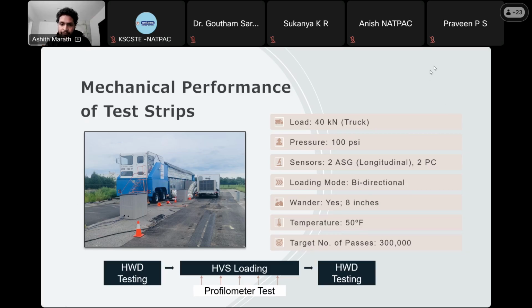And the testing plan was to conduct HWD testing. Again, the HWD is the heavyweight deflectometer, which is typically used on airport runways, and it has a higher loading level than the FWD. We had an HWD in our facility, and the plan was to conduct HWD testing before HVS loading, and then conduct the HVS loading. As the loading progressed, we took multiple measurements of the profile using the laser profiler to measure the permanent deformation on the pavement. And at the end, we again did the HWD testing to compare the before and after loading conditions of the pavement.